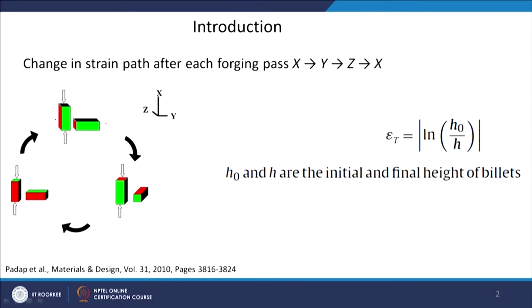So, in x, y, z, three different directions, the amount of strain which you put in is very simply the logarithmic strain, which is the true strain. The initial height divided by the final height of the billet, taken as a logarithm, should give me the strain which you are imposing in the material in each forging pass.